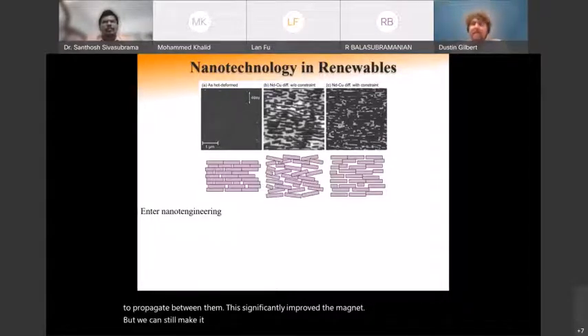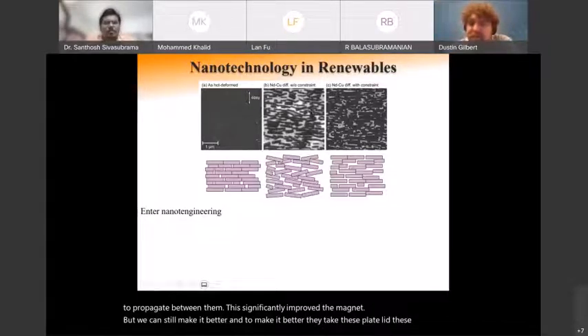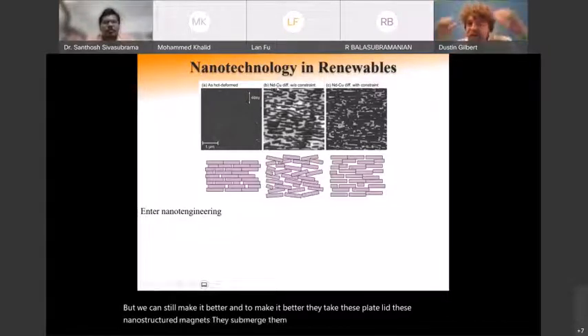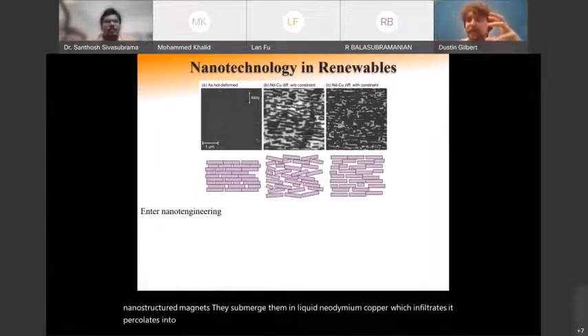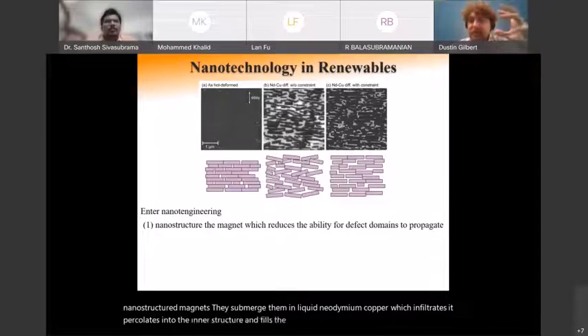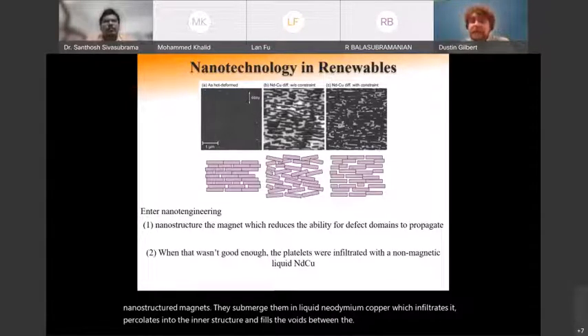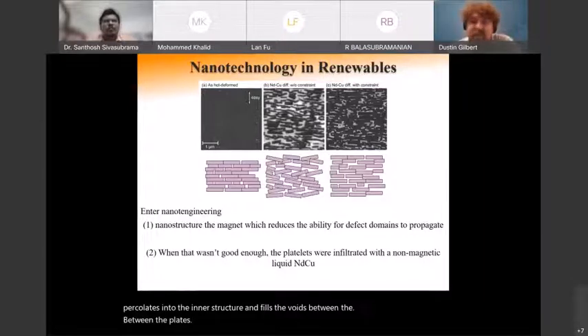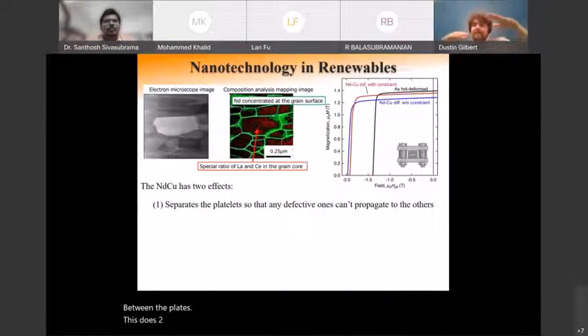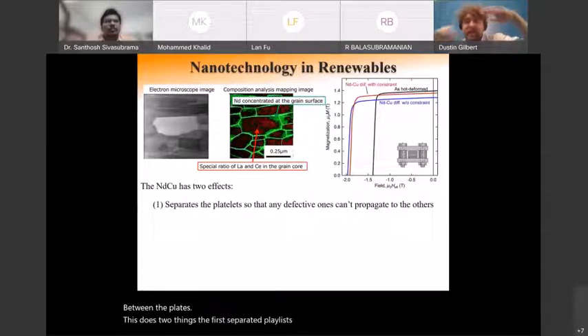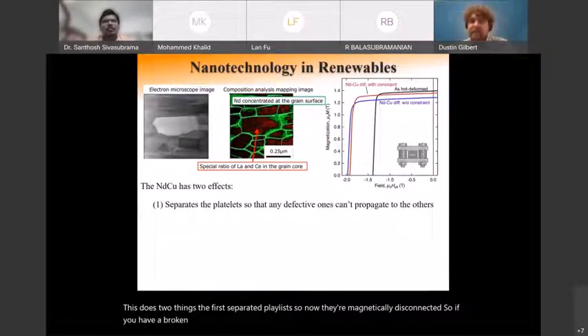And to make it better, they take these platelet, these nanostructured magnets, and they submerge them in liquid neodymium copper, which infiltrates. It percolates into the nanostructure and fills the voids between the platelets. This does two things. The first, it separates the platelets. So now they're magnetically disconnected. So if you have a broken platelet, a defect, it doesn't propagate and destroy the rest of your magnet.